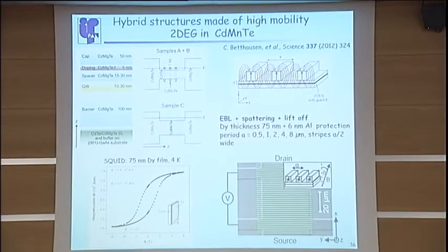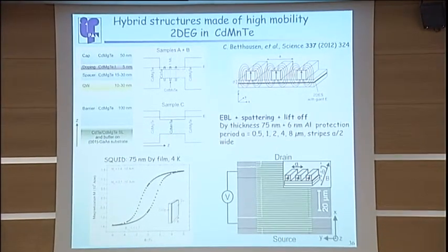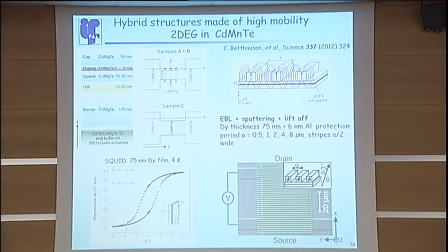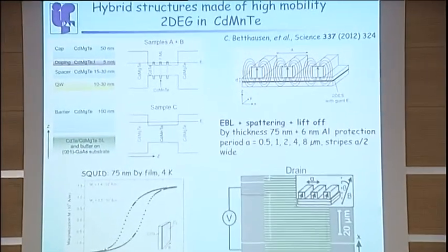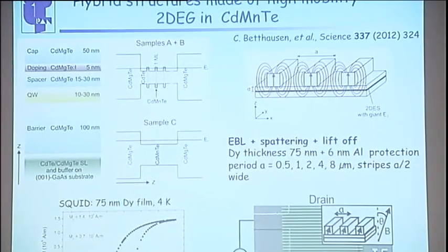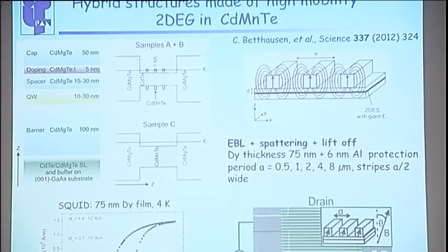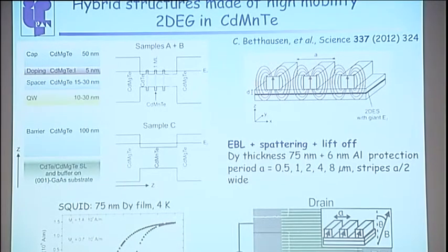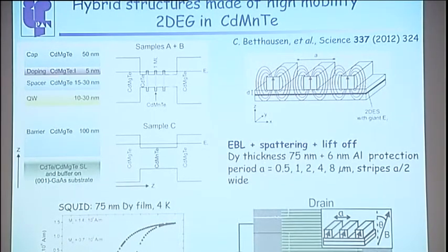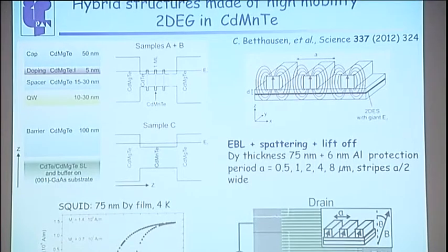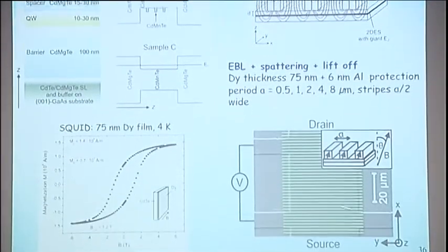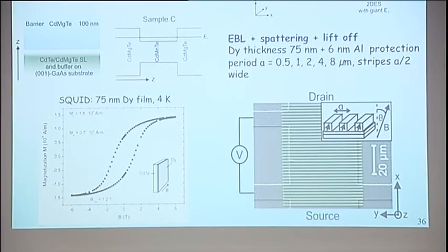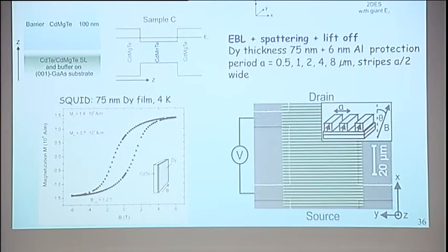So different samples were used, both with manganese introduced digitally or homogeneously, and e-beam lithography, sputtering, and liftoff. On the surface of the samples, stripes were produced with a period from 0.5 up to 8 micrometers, and the stripes were half of the period wide. Here is the scanning electron microscopy image of one of the devices, and those are the stripes. This is false color. But here in the inset there is the configuration.